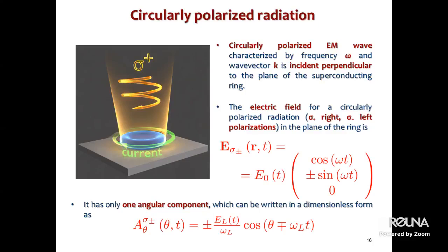Next, we apply a circularly polarized electromagnetic wave, characterized by frequency omega and wave vector k, and it is incident perpendicular to the plane of the superconducting ring. For the electric field of circularly polarized radiation, sigma plus is for right polarization, sigma minus is for left polarization, and it is in the plane of the ring, and is given by this expression. The total vector potential A has only one angular component, which can be written in dimensionless form as provided here.